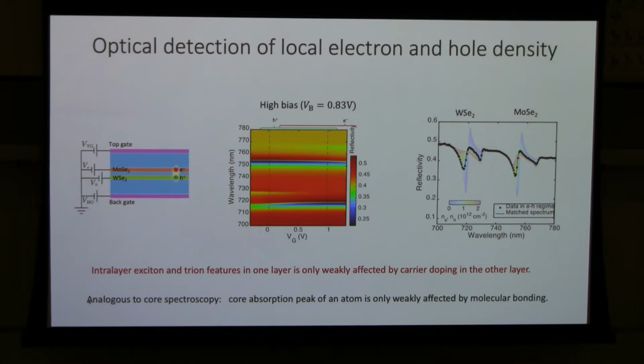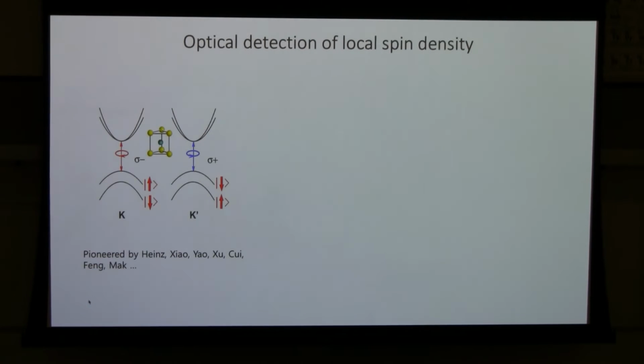Because of this effect, we can use this calibrated spectrum and carrier density method to determine, at every position, the local electron density and the local hole density using optical spectroscopy. In addition to measuring the charge density, it turns out the optical spectroscopy in transition metal dichalcogenides also provides a powerful way to measure the spin density.